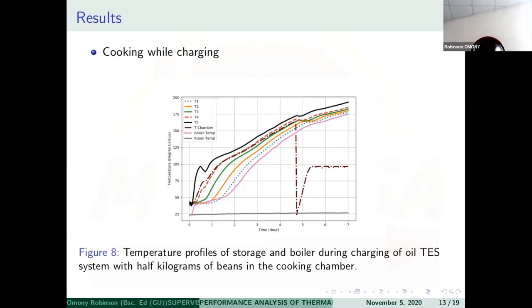So in this case, the oil test was charged to about 160. Then half a kilogram of beans was added into the cooking chamber and cooked. Of course, as you can see, the beans and water at a temperature of about 24 were added into the chamber, and the temperature in the cooking chamber kept on rising up to a maximum point of about 98, and that is fairly a good cooking temperature. And the beans were able to get ready in about 2 hours 10 minutes.